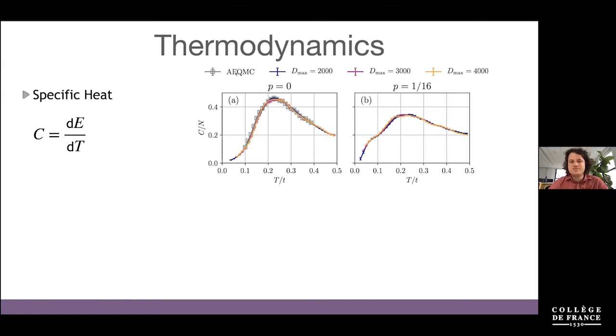Moreover, at half filling, as I've told you previously, there's auxiliary field quantum Monte Carlo, which is exact. So we can exactly compare our results to this AFQMC method, and it also agrees nicely. What we see in the specific heat at half filling is this quadratic behavior, which is expected for an antiferromagnet, and this broad peak around a temperature of 0.2. Now, if we dope the system, this peak remains at the same position, but there's a shoulder in the specific heat developing at a temperature around 0.05.